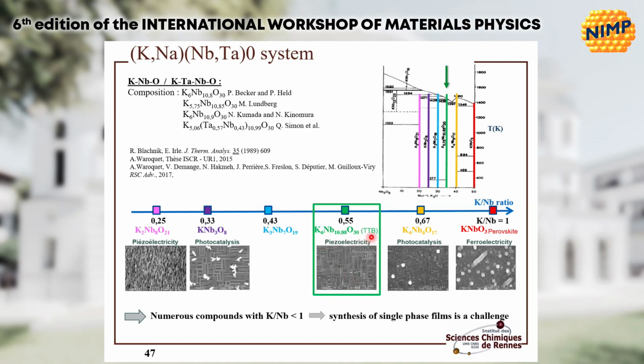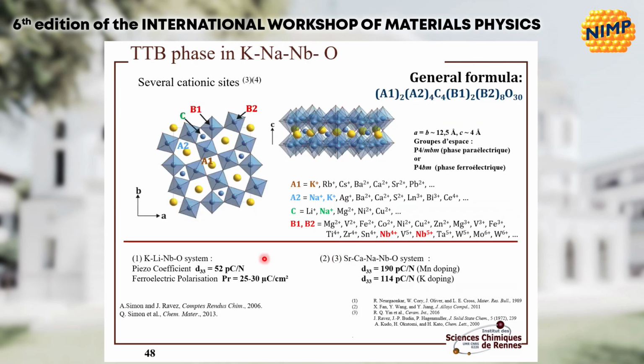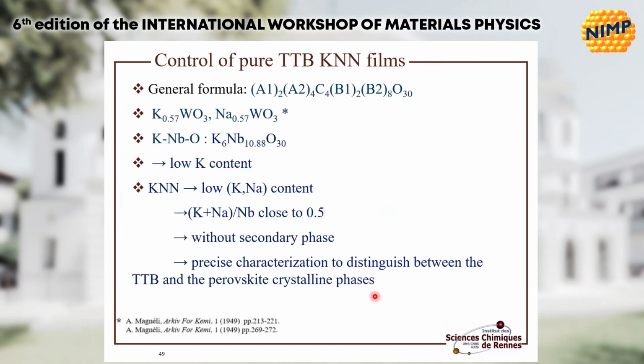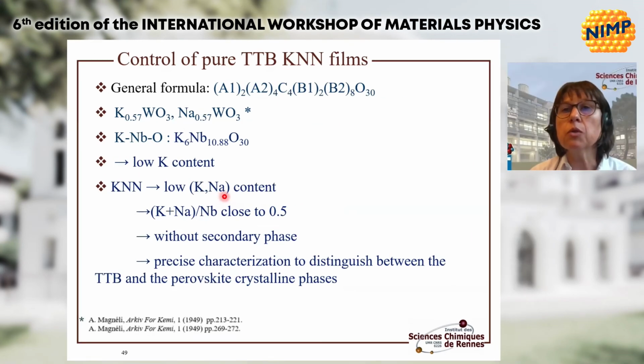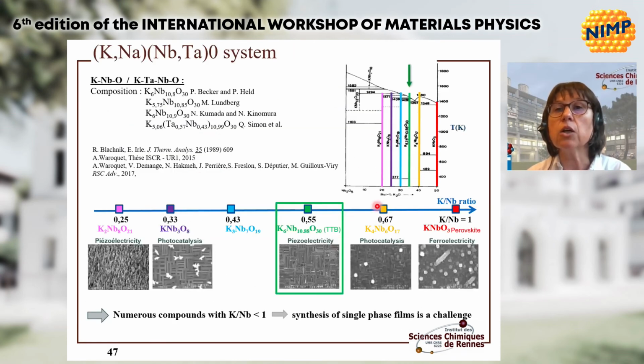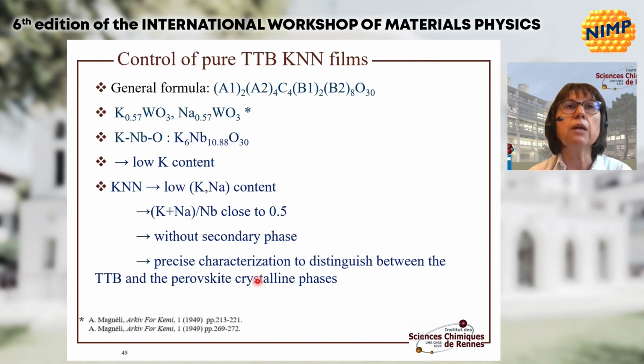This is the TTB, tetragonal tungsten bronze phase, that is reported for several compositions to be piezoelectric. Indeed, you can see here two other systems reported over the years to present quite high piezo coefficients. Only a few data are reported on TTB in potassium niobates, and only a few reports in thin films. So what is the challenge? The challenge is to control, in KNN, low potassium and low potassium-sodium content, typically close to 0.5, without secondary phase. And you have seen here that there are many phases that can compete. So this is really a challenge to obtain this pure phase.